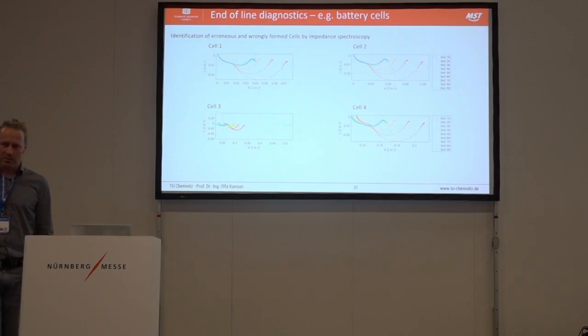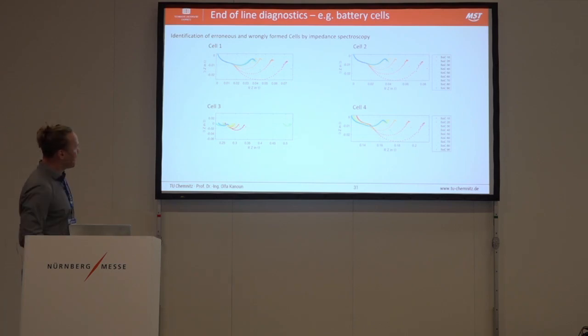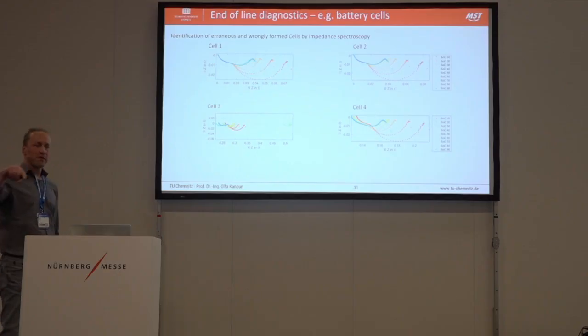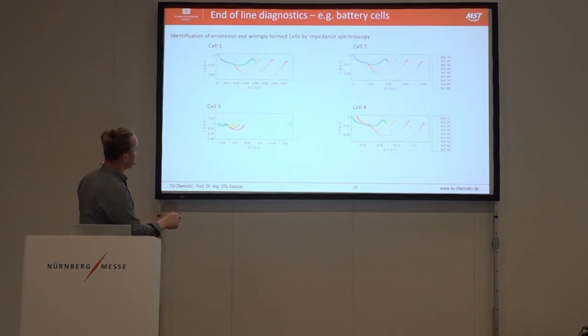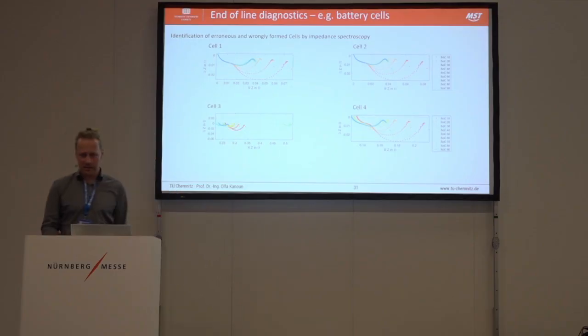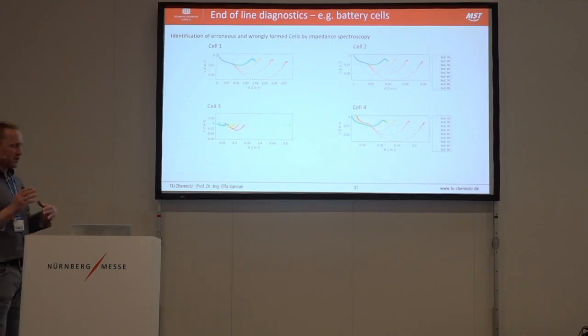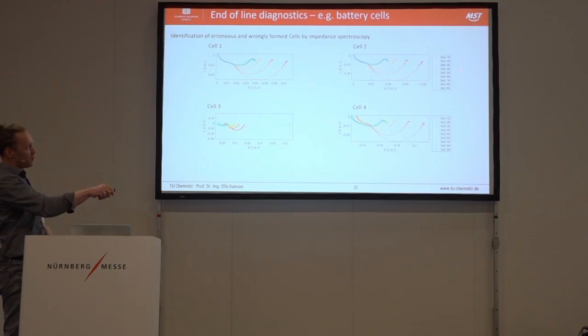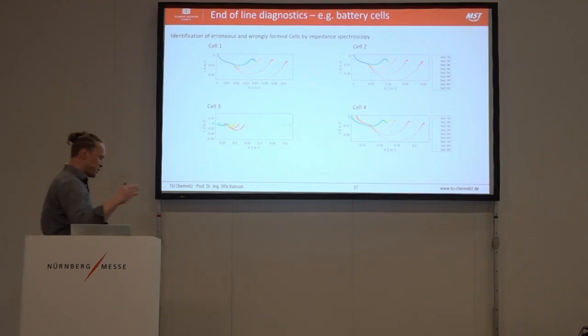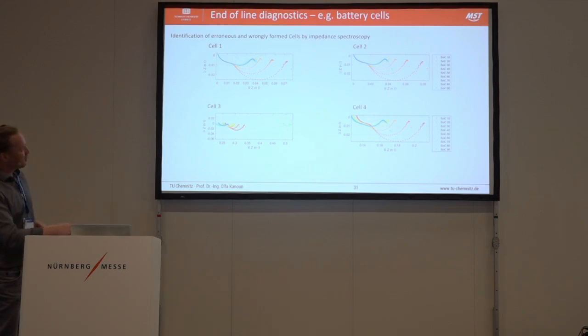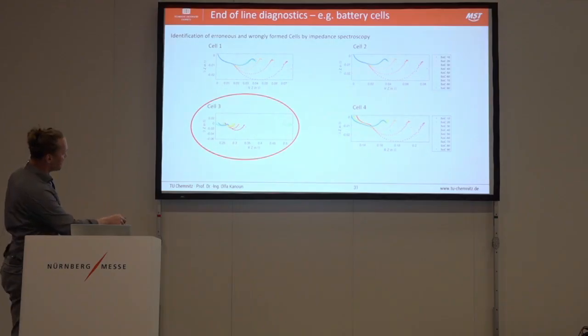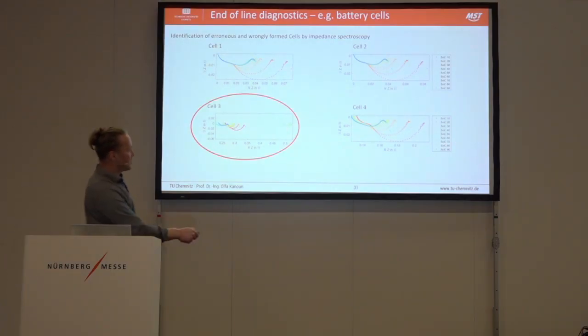End-of-line testing. Here I want to speak about our battery diagnosis. The battery is maybe a product of end-of-line production, and here you see a comparison of four cells of the same type. And what did we do? We measure impedance spectra at these SOC stages. What is the procedure? We charge the battery fully, we discharge to evaluate the complete SOC range. Then we go in steps of 10%, and then we measure the impedance spectra. And we see here cells 1, 2, and 4 are almost similar, and cell 3 has a shift, especially here at 70% SOC.